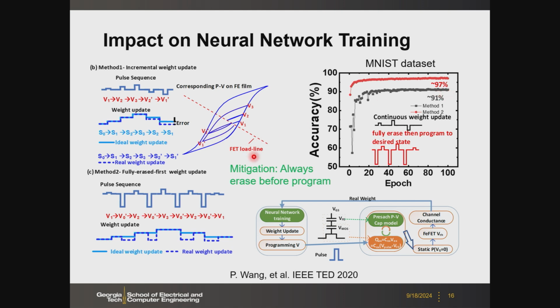One possible mitigation is that we always operate on the saturation loop. That means every time we program to an intermediate state, we erase to the ground state, and then go from there. We do not do this kind of manual tuning in between. We always go to the ground state and then go up again. Of course, this brings overhead, with additional latency and energy for the erase pulse. But at least this is one possible solution. Anyway, after so many trials, we believe that training might not be the immediate or tangible application at this moment. That's why we focus most on the inference of this technology.